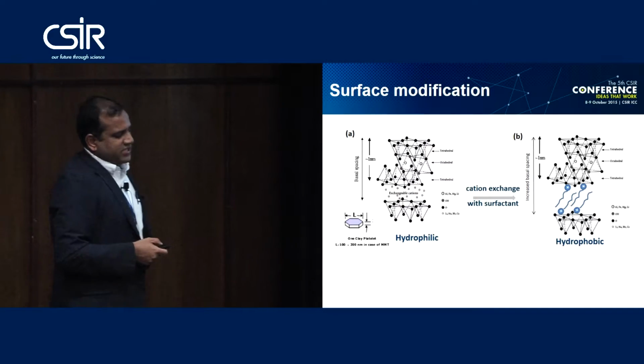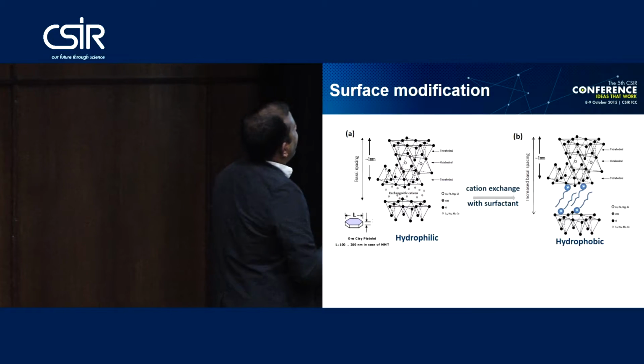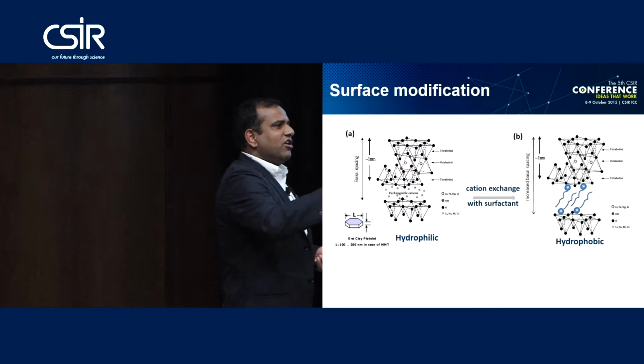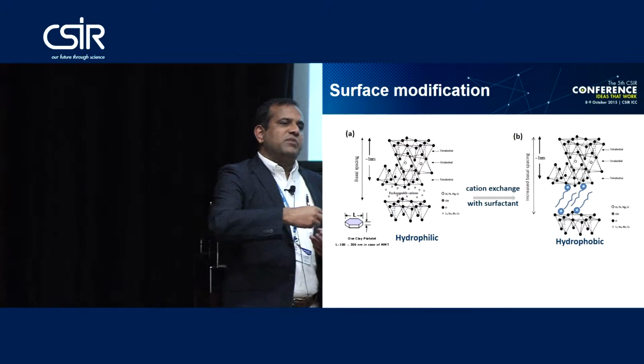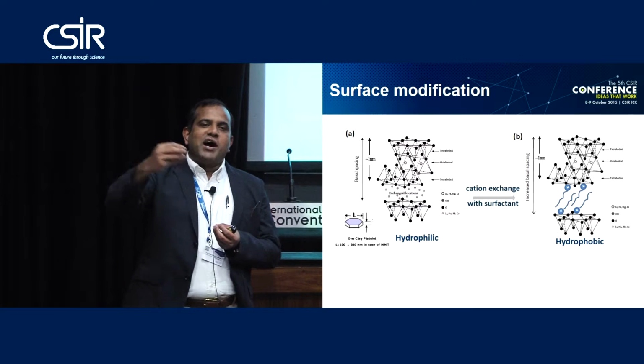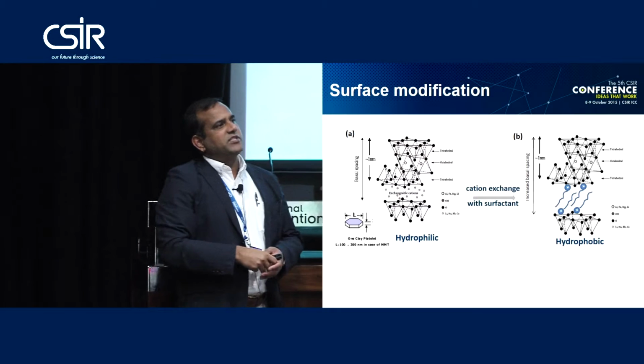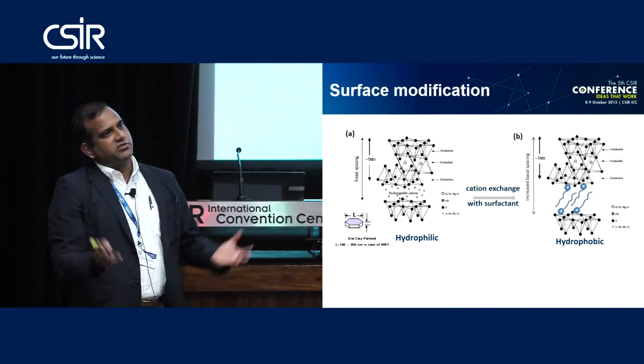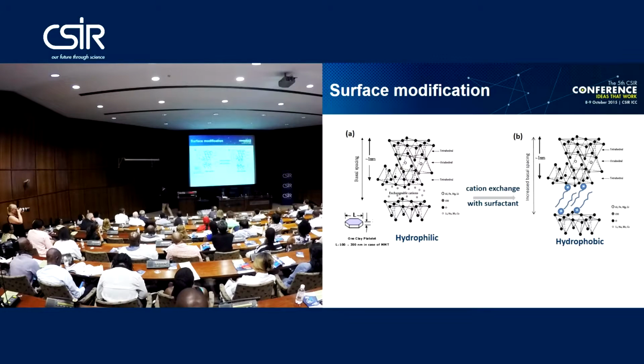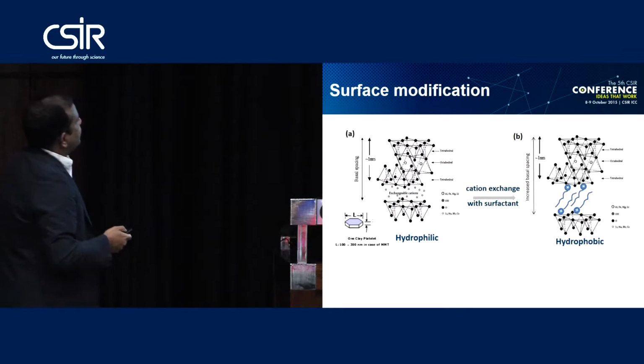You can do a number of chemistries. Because there are a number of hydroxyl groups on the surface of the clay, you can do a lot of chemistry at the nanoscale. You can polymerize your monomer on the surface of the clay. You can also graft different kinds of small macromolecules on the surface of the clay. Or, because clays contain a good amount of sodium, potassium or calcium cations inside the clay gallery, you can replace those cations with surfactant, and when you do that, you can convert the hydrophilic surface to a hydrophobic one.